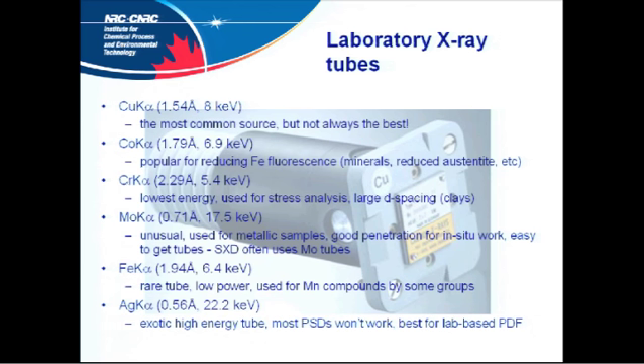Silver. This again is a pretty odd one. It's pretty exotic and often quite useful for things like PDF work where you want to get to high Q. Practically speaking, this is the highest Q range you will be able to get for PDF work in a lab, using this particular tube. Also you've got penetrating power, so you can start punching through materials for non-ambient cells. And I'll be showing an example of that later.